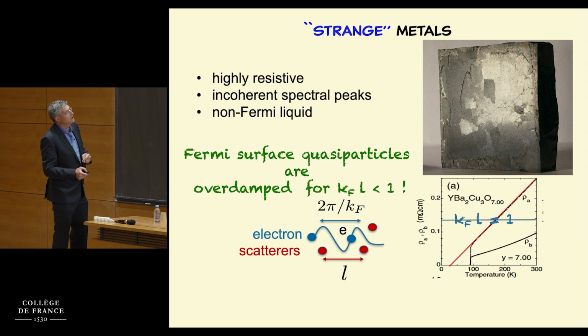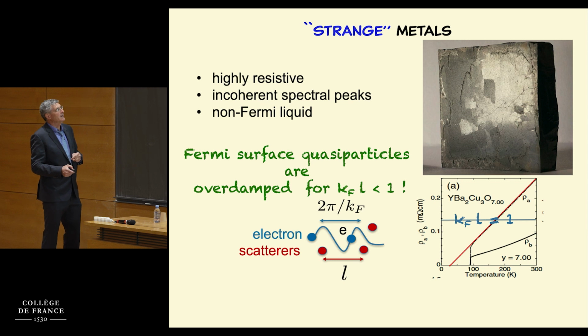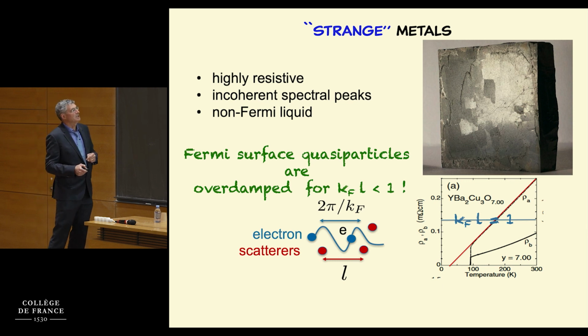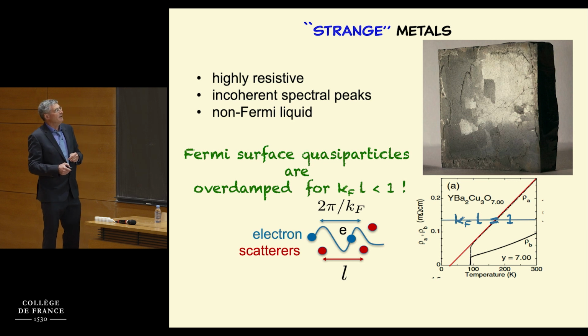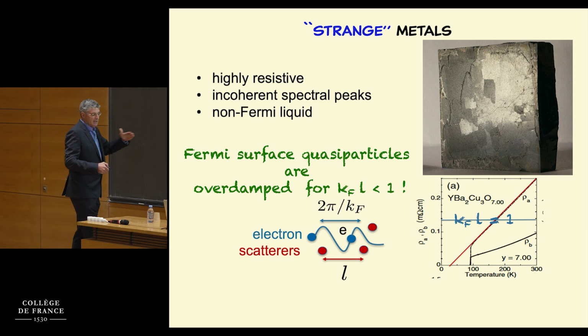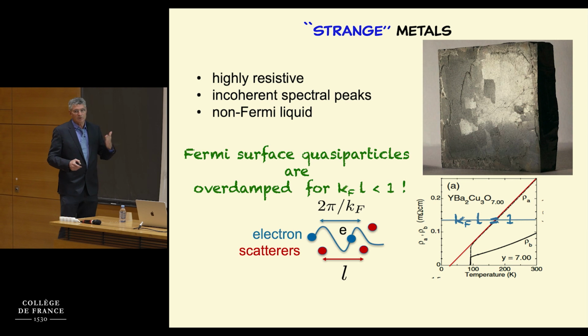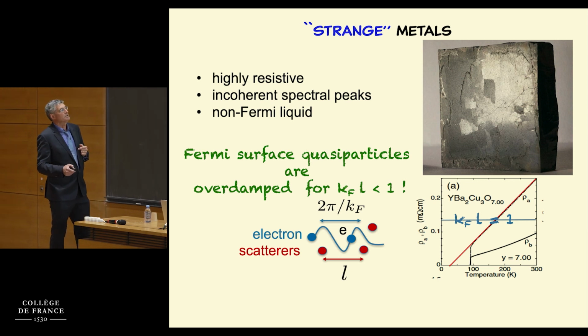So we noticed that if we just plot the resistivity versus temperature, it goes up and up and up in temperature. And if you cross this line, it's called the Ioffe-Regel line, it means that the distance between electrons becomes the same order as the distance between scattering. So you have no well-defined free electron theory, actually, to describe the transport above these temperatures.